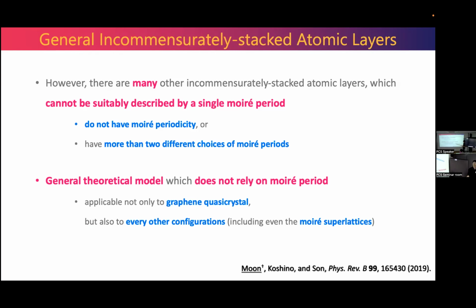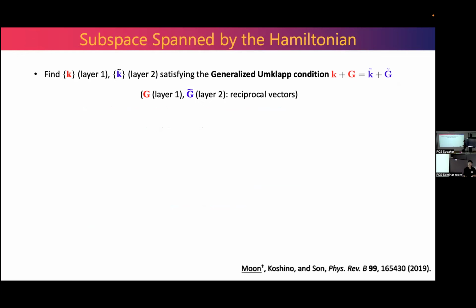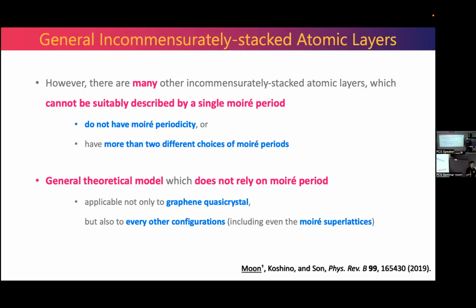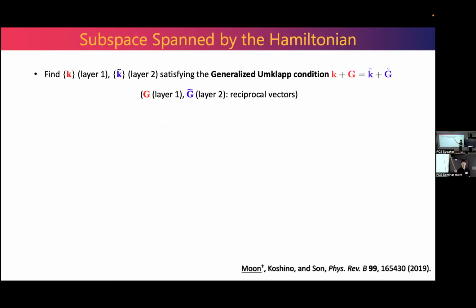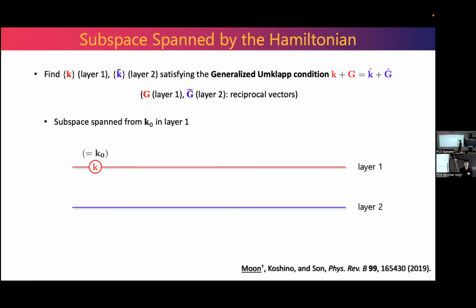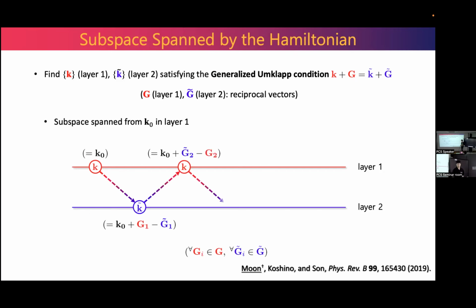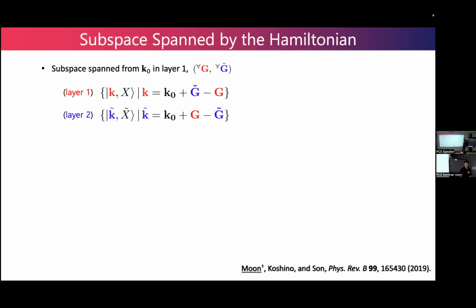However, there are many systems which do not have periodicity or have more than two different choices of moiré period. So I define a new subspace. Find the subspace for K and K tilde verifying the generalized Umklapp condition. Starting from K naught in layer 1, it scatters to K tilde, which satisfies this condition. And it scatters back again. And we can write the subspace in this way.